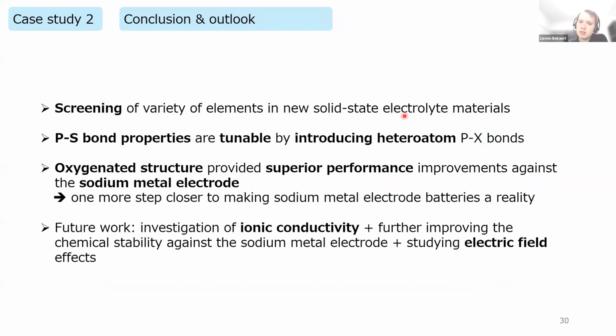So to conclude this example, we performed a screening of a variety of elements in new solid state electrolyte materials. And this is thanks to Matlantis to be able to simulate these many different elements. We also confirmed that these PS bonds are tunable in property by introducing these heteroatoms, and that the oxygenated structure provided a superior performance against the sodium metal electrode.